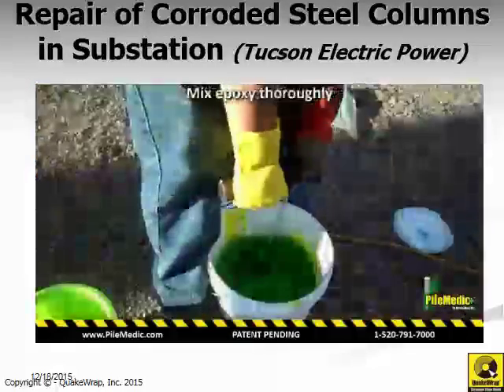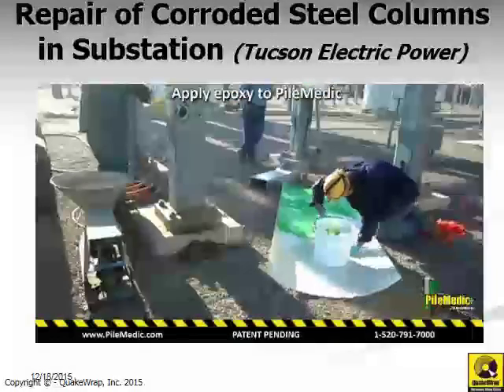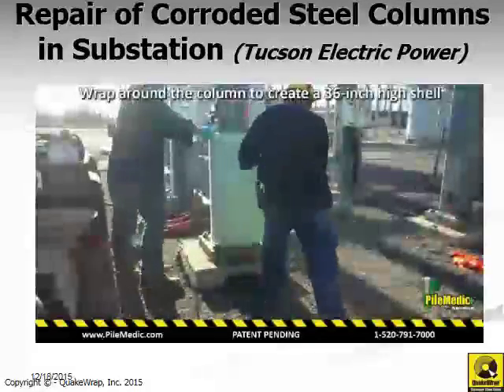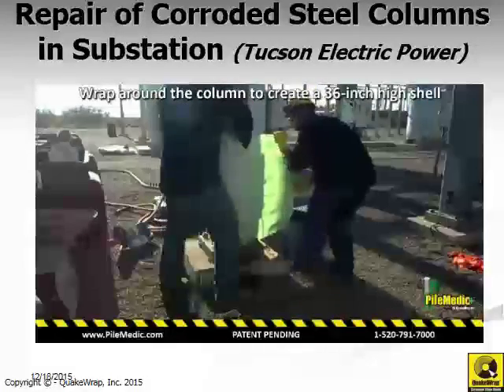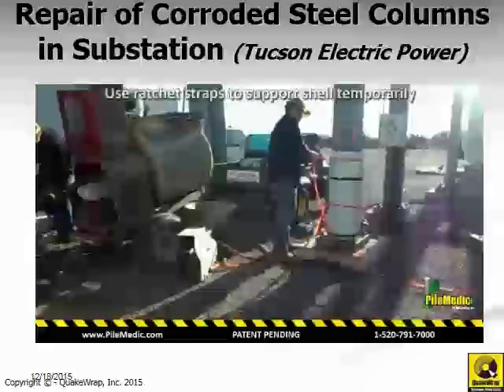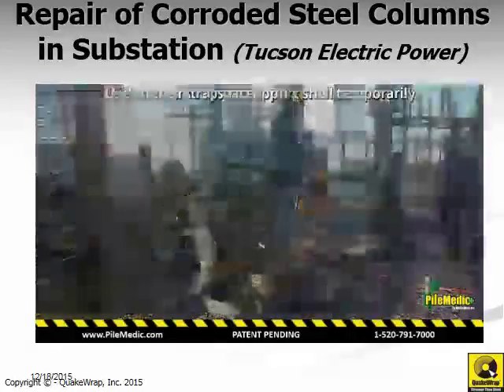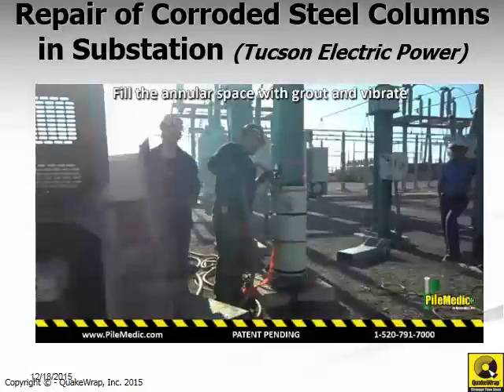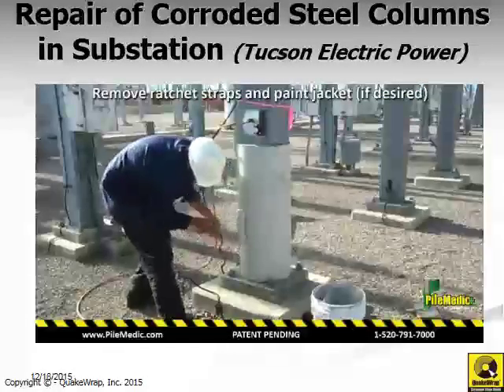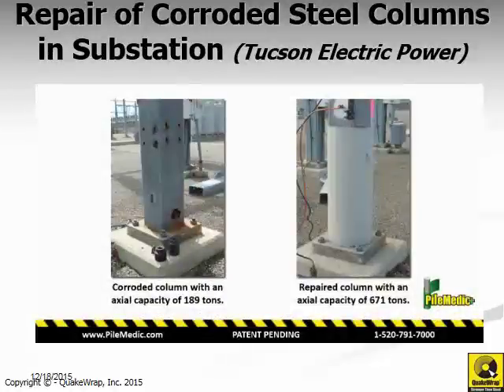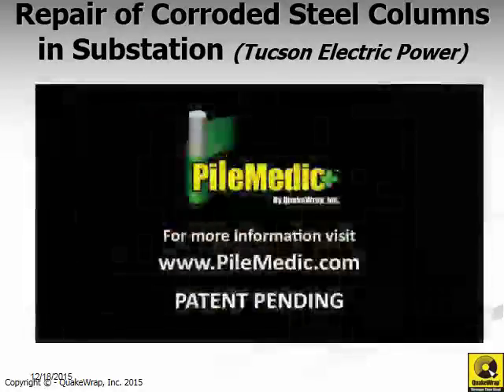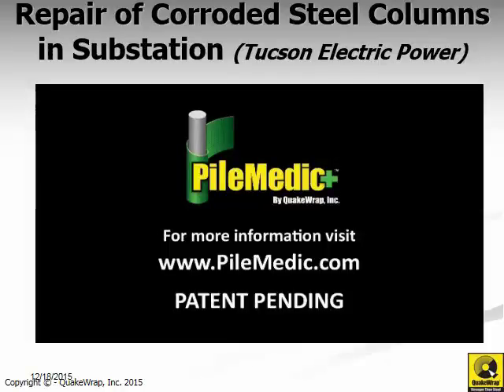Then we cut this laminate to the desired length, put some epoxy on it, and wrap the laminate around the column. You'll notice you can bypass the anchor bolts and so on. We hold the jacket together with a ratchet strap and fill it with grout. And at the end, we put a weep hole, which you can see, to allow water to drain out of the pipe. So this type of repair can be performed while the substation is fully operational and all of the lines are energized, saving the owners significant money.